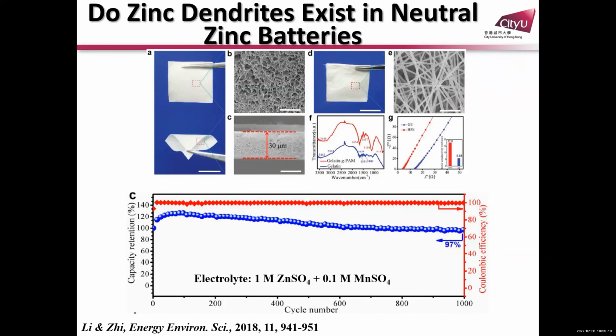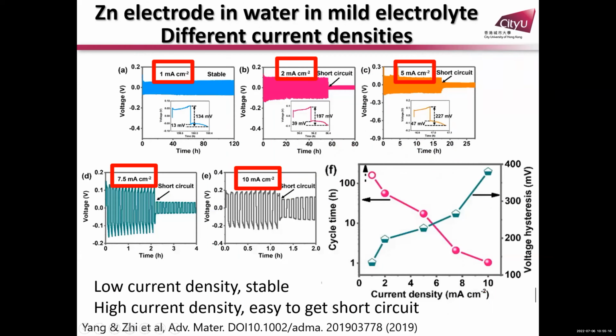So I got confused: is there any zinc dendrite in the mild electrolyte? I asked my student to investigate. Put zinc anodes in symmetrical batteries, and you will find that at different current densities the cycling time is quite different. If you increase the density from 1 to 10, the cycling time drops from 120 to around 1 level. With the increase of current density, cycling time decreases a lot. So if you claim there are no dendrites, it is possible; if you claim there are dendrites, it is also possible, because you have different conditions.